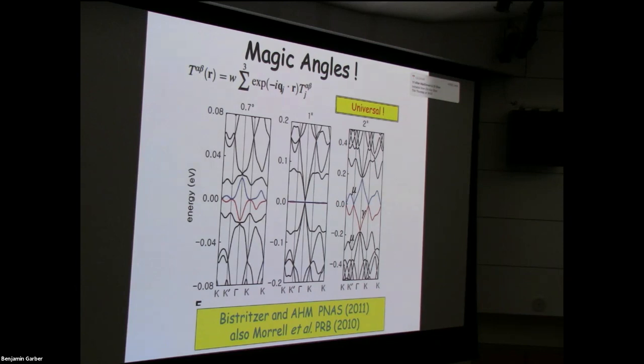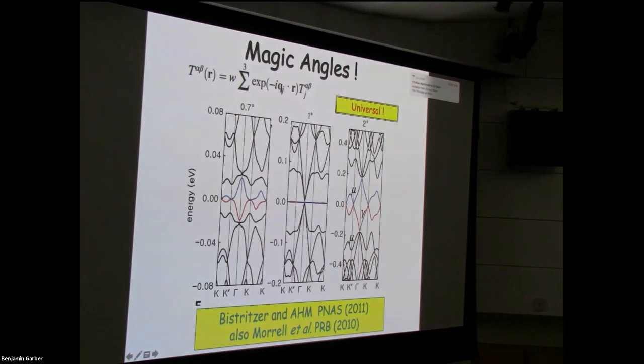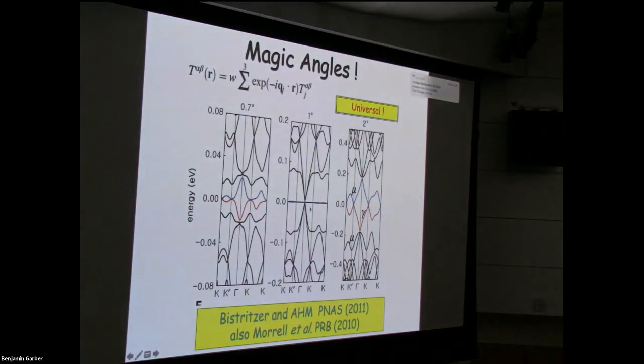It's not surprising, perhaps, that the velocity of the electrons in the graphene sheet slows down as the layers get more strongly coupled to each other. And what we discovered in this work numerically is that there is a magic twist angle, actually a discrete series of magic twist angles, at which the velocity of an electron at the Fermi level of graphene crosses through zero. And if you look at the average velocity in these energy versus momentum plots in the mini-band Brillouin zone, it's smaller than in a single graphene sheet by a factor of about 10 to the 3 to 10 to the 4.